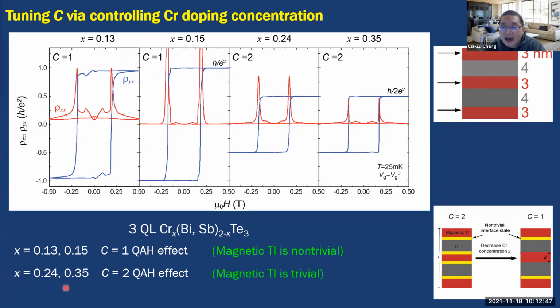And at the higher magnetic doping level, this magnetic TI will become trivial. So there will be two quantum anomalous Hall layers here. It's just a series connection. That's the reason we could realize the C equals 2 quantum anomalous Hall insulators here.